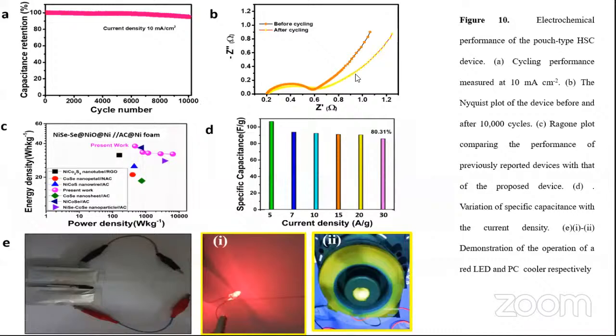Figure B shows the Nyquist plot showing the solution and the charge transfer resistance corresponding to my material, which was also low, around 0.2 and 0.4 respectively. And you can also see before and after cycling, the value does not change drastically.